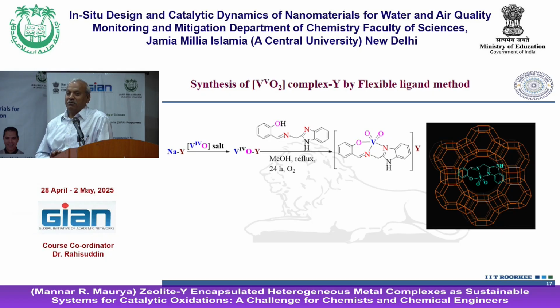Okay, paramagnetic, diamagnetic, because characterization of diamagnetic becomes a little easier, so we have used air. So vanadium 4 oxidized to vanadium 5, and the ligand attaches there, so that will form a double bond, V double bond O, V double bond O, two oxo groups are attached there, and it can be seen this way, vanadium complex encapsulated with the zeolite. Characterization becomes a little easy, because then two cis bands can be seen very easily.